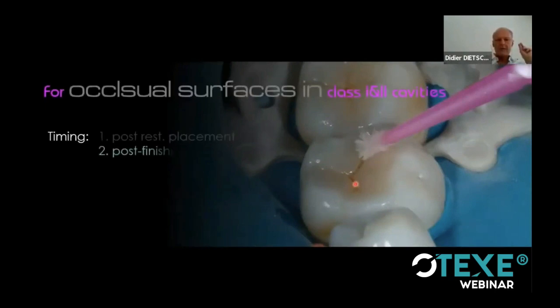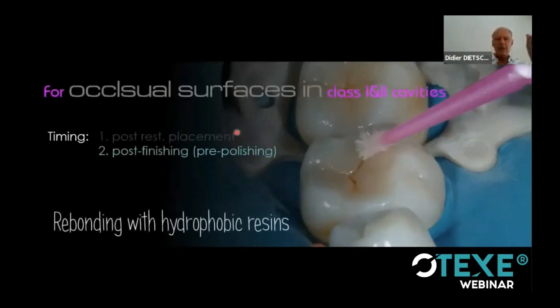So the timing now, initially we were doing the rebonding just after finishing the placement or the sculpting. And we found that the best moment is to proceed with the finishing, but before the polishing. If you use silicone instruments, then you will create a smear containing silicone, and then nothing is sticking anymore, neither to the tooth nor to the restoration. So you must do it after finishing using fine diamonds or discs, but not after using silicone instruments.